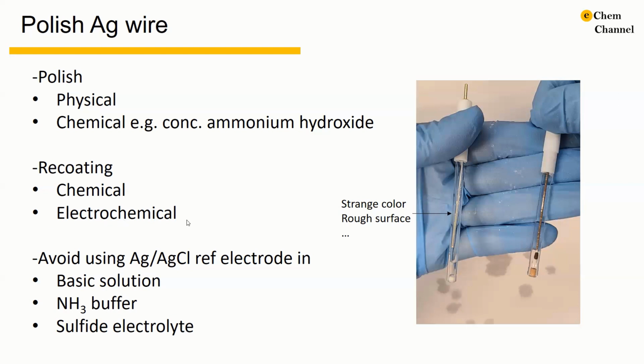For the electrochemical methods, what we can do is put the freshly polished silver wire back into potassium chloride electrolyte. Then we make a two-electrode cell with the reference electrode as the positive electrode and the platinum electrode as the negative electrode. And we just give a very, very small current, such as 10 microamperes overnight. We will be able to have the silver chloride coating on the silver wire.